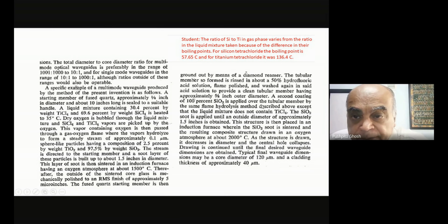over which they made their film. Okay. So now whatever they applied first will become the core. Now they have to put the cladding. A second coating of 100% SiO2 is applied over the tubular member by the same flame hydrolysis method described above, except that the liquid mixture does not contain TiCl4, so you get pure silica. The SiO2 soot is applied until an outside diameter of approximately 1.5 inches is obtained. So that's what you have.